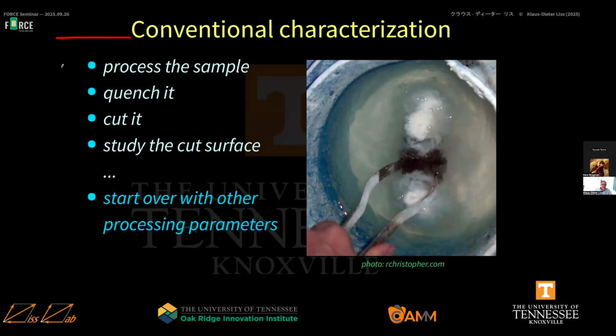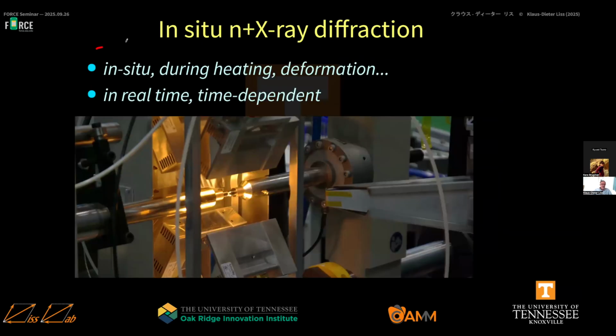Conventional characterization is you process the sample, you quench it, you cut it, and you study the cut surface with a microscope, maybe some XRD, which goes in a few micrometers, and so on. And then you start over with other processing parameters. So what we do is in situ neutron and X-ray diffraction. That means in situ during the heating or during the plastic deformation, or something is going on in real time, so we can get time-dependent information.